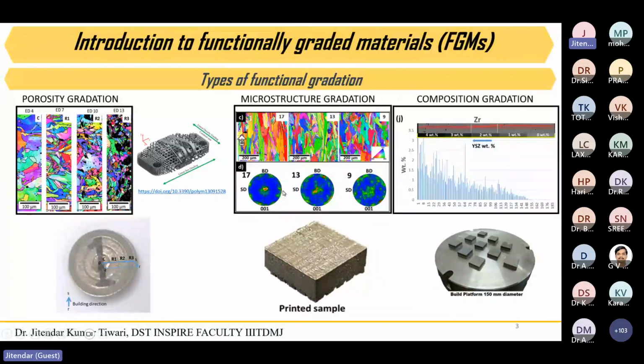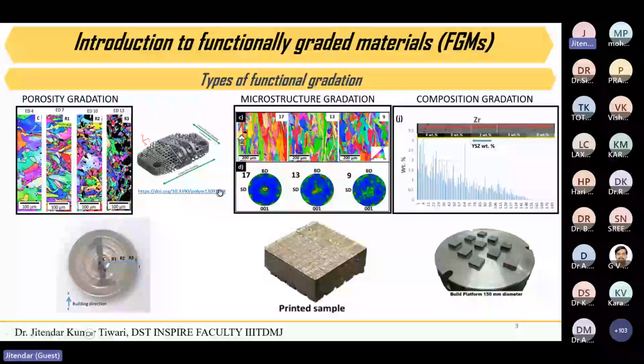Another one is that without changing the material, we can achieve different kinds of microstructure in a single material by just varying the parameters. The first sample you are seeing here is printed on the SLM Solutions machine, and this one is printed on the Intech iFusion SF1 at IIT Madras, and these samples are the compositionally graded samples, which were also printed at IIT Madras. Here, from the center to the outer region, the porosity is increasing because the parameters of these concentric discs are different, and since the parameters are different, the fraction of porosity is different.